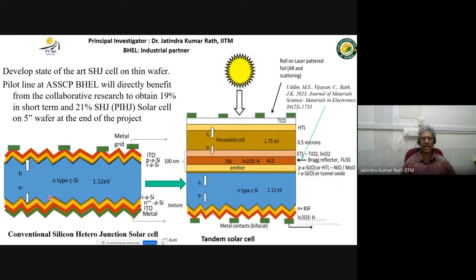These are the main efficiencies in the world at present for single junctions. And we want to make this kind of cell and utilize it to make tandem cells like this. The only thing is it should be flat, not textured, as we are doing. Because it is flat, with no texture, the light goes straight in. The light trapping only comes after texture, after scattering from here, but there is no scattering from the top, which reduces the amount of light absorbed in this material. As crystalline silicon is an indirect band gap material, you need a lot of thickness to absorb all the light.